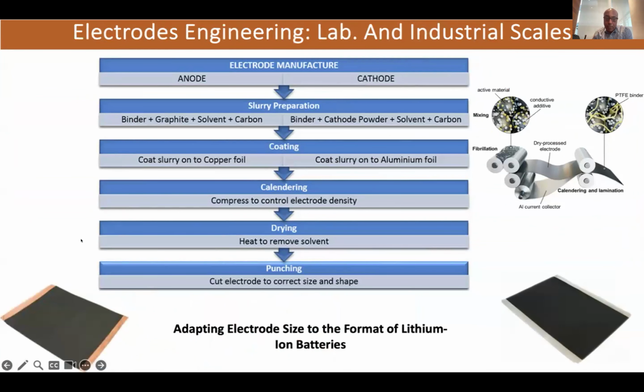For the engineering, this is very important because in Morocco we need to get this expertise of engineering, not only at lab scale, but also at industrial scale. So how to proceed? The process is the same on the anode and the cathode side. What we do is prepare a slurry composed of the active material, which is graphite on the anode side. We add the solvent, sometimes organic, carbon to enhance the conductivity, and the binder to have good mechanical cohesion of the particles.